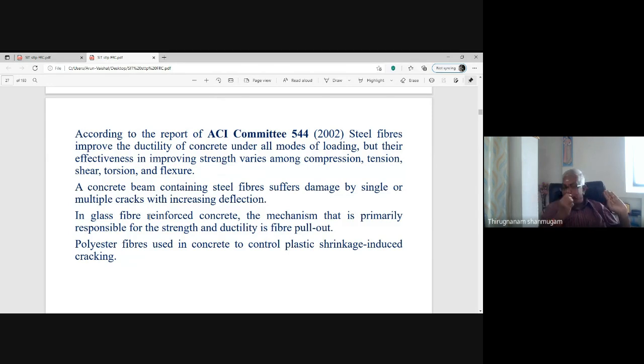So for the improvement of ductility demanded by the seismic behavior of the structure, or the behavior under wind, cyclone or hurricane, which demands large ductility, you have to go for steel fibers. But their effectiveness in improving the compressive strength or tensile strength or shear strength or torsional strength or flexural strength is very low compared to this ductility. Even if the ductility improvement is 100%, the improvement in strength is only 25 to 30%.